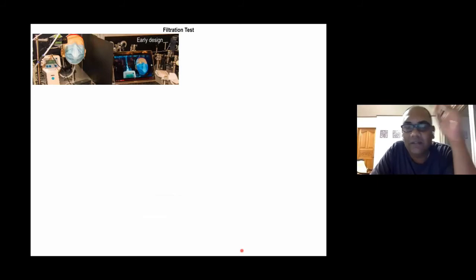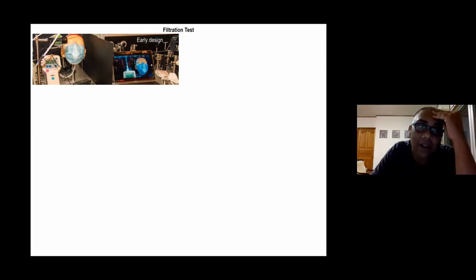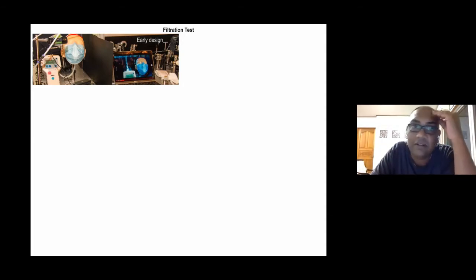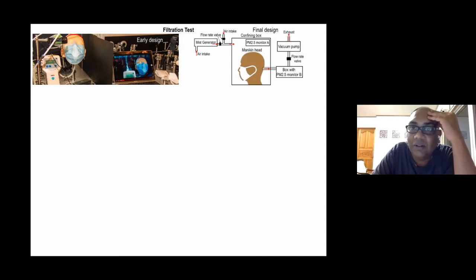Now that I have done the structure, we did the filtration tests, and I'm showing you a snapshot of an early design that did not work. We scratched our heads, and for this I got a lot of help from Shankar Ghosh. Initially, for the particle counter, I was using what is used for counting particles in clean rooms. After chatting with Shankar Ghosh, I realized this was a mistake because they can only count particles of diameter 5 microns and above, whereas for the N95 you have to go down to 0.3 micron. So the final design, as in the schematic shown here, was generating aerosol particles in water with salt, sodium chloride.